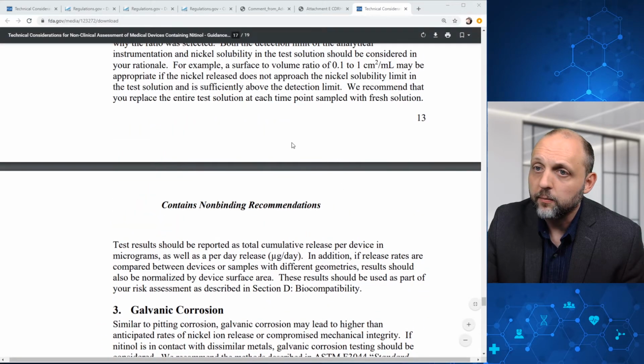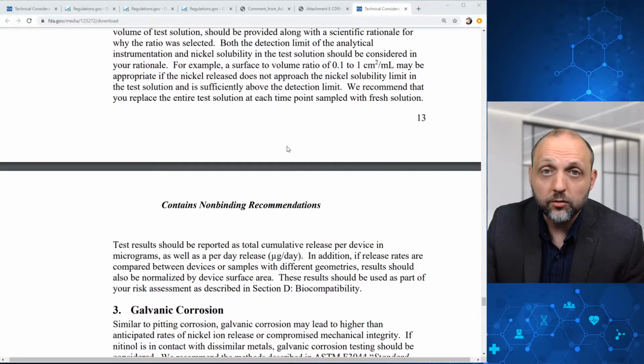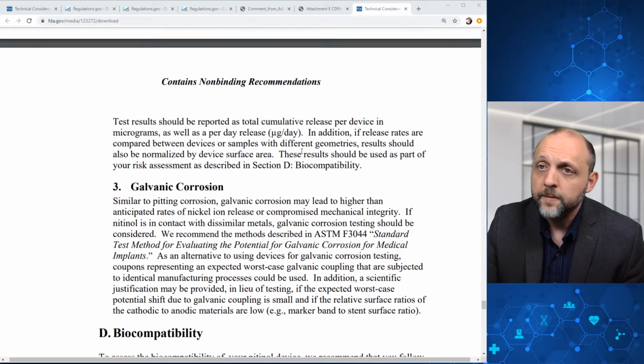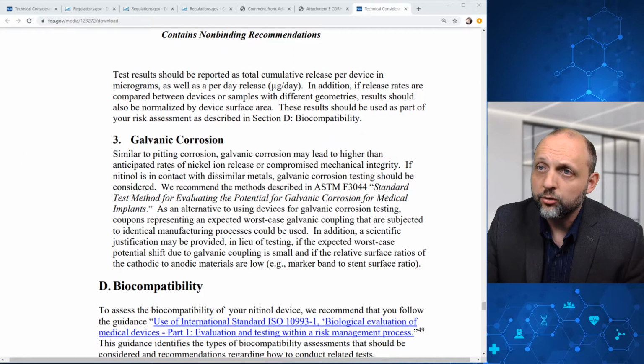And there's some additional recommendations. If you're going to do this testing, read through and make sure you follow all of these recommendations in this section. And then in terms of galvanic corrosion, similar to pitting corrosion, galvanic corrosion may lead to higher than anticipated rates of nickel ion release or compromised mechanical integrity. If nitinol is in contact with dissimilar metals, galvanic corrosion testing should be considered. FDA recommends the methods described in ASTM F3044.